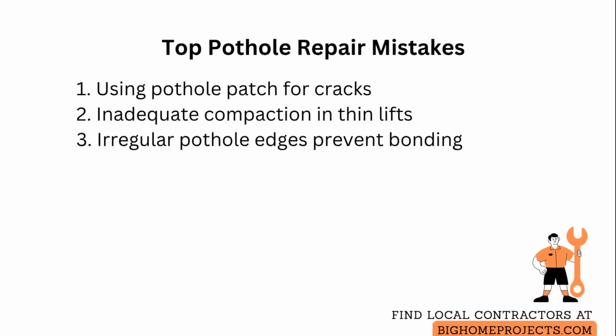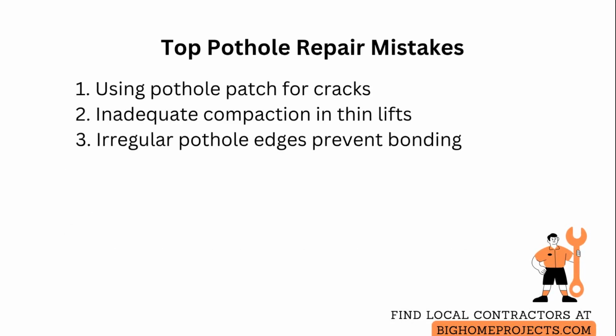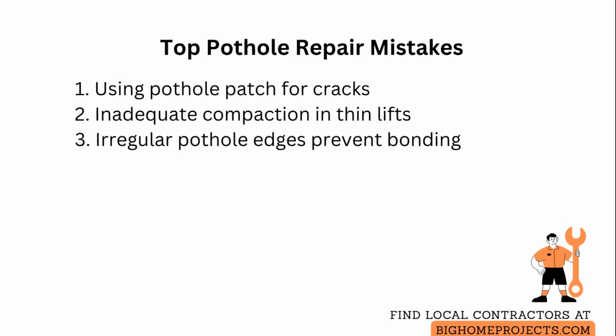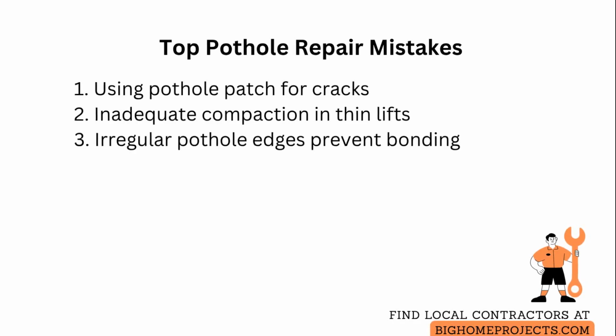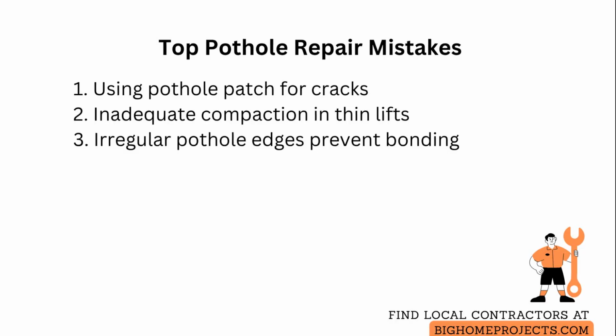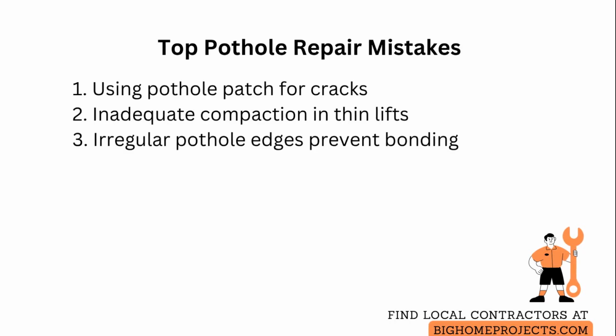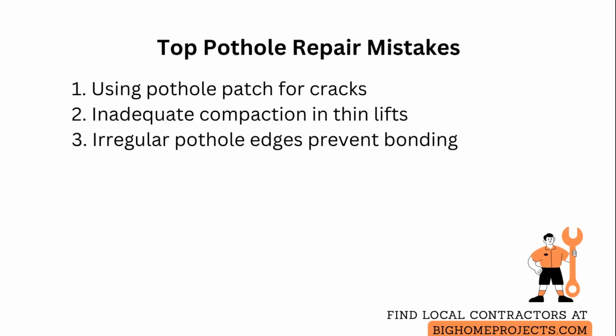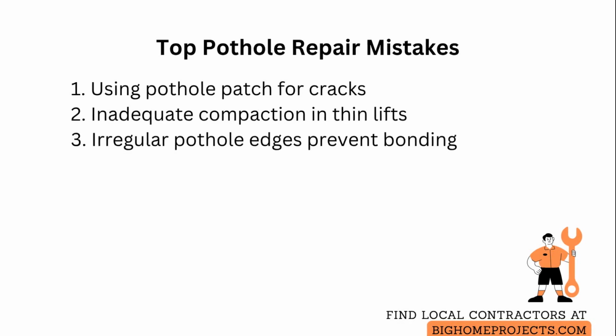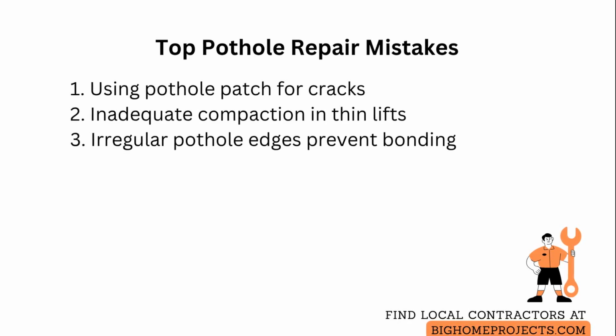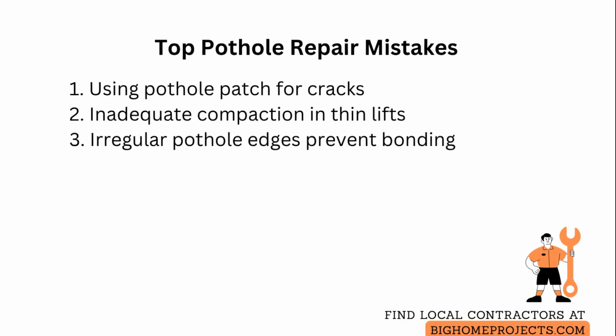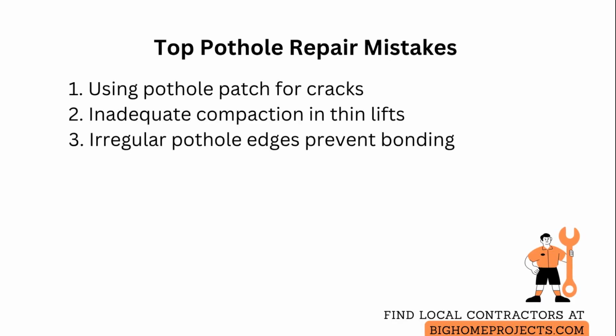Common mistakes include trying to fill cracks with a cold patch meant for potholes, which will not adhere in thin joints and can ravel. Use a hot pour crack sealant or cold pour crack filler and backer rod for wide cracks. Another error is failing to compact in thin lifts, which causes quick settlement. Compact each layer fully and do not exceed 2 inches per lift when using hand tamping.